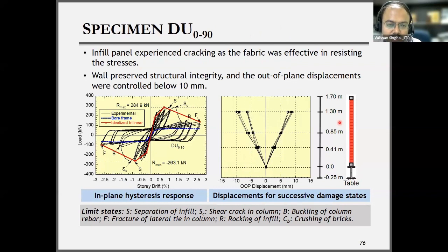The specimen with the direct application, even though it was unanchored, has shown better performance. You will see the separation was delayed. You can see here the S was at a later stage, and the drop in strength after reaching the peak was much more gradual compared to the previous one. It has also been seen here that the out-of-plane response was more uniform, and we could not see any significantly large out-of-plane displacement as compared to the other unanchored scheme.